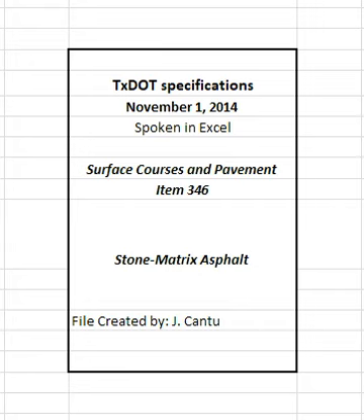If the optimum asphalt binder content for JMF2 is more than 0.5% lower than the optimum asphalt binder content for JMF1, the engineer may perform Tex 248F on Lot 1 to confirm the mixture meets the overlay test requirement of 200 cycles. Verify that JMF2 meets the mixture requirements in Table 4.